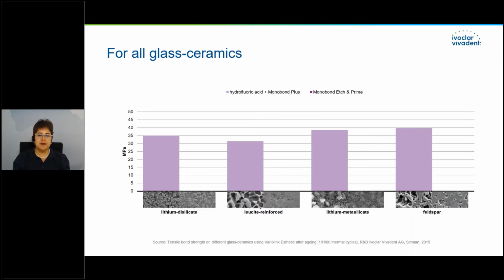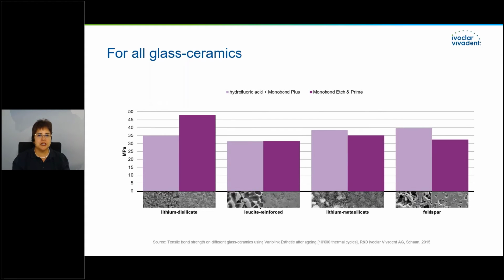Monobond Etch and Prime is suitable for conditioning of different glass ceramics. The investigations shown here, including specimens of several types of glass ceramic, of pure glass ceramic, not the hybrid ones, show that it is comparable to the pre-treatment with hydrofluoric acid and Monobond Plus, even after thermocycling.